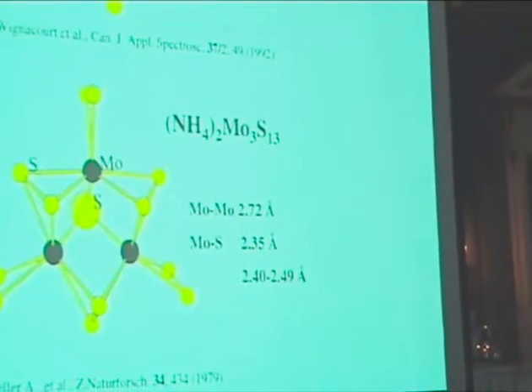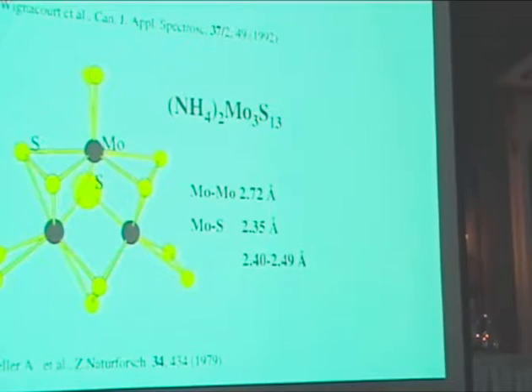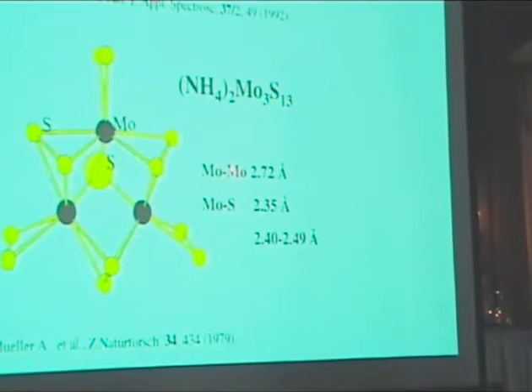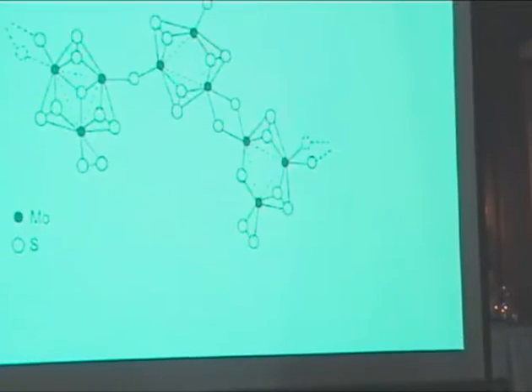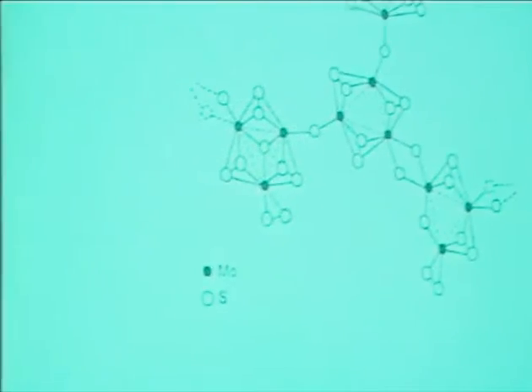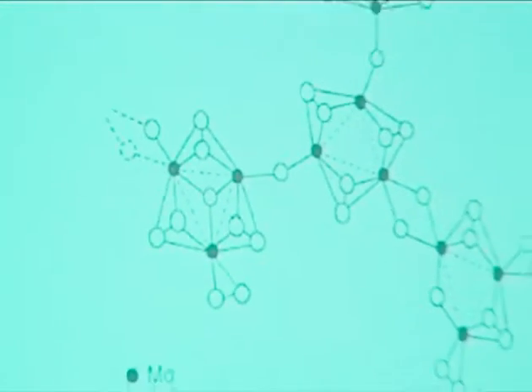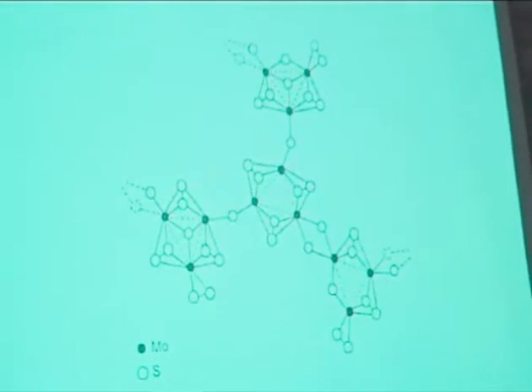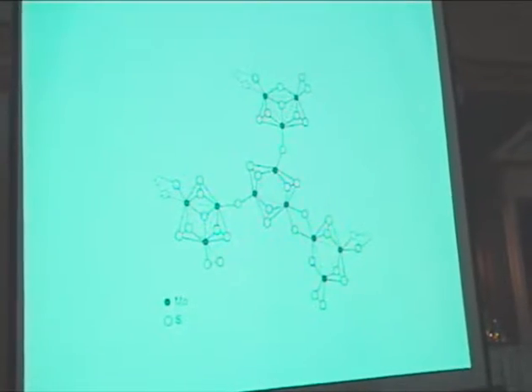And the analysis of the spectrum was that in that case you also have two peaks. One was the molybdenum-sulfur, one was the molybdenum-molybdenum. So we think that the intermediate is an amorphous state. Nobody has ever been able to crystallize this intermediate state. And we believe that it is because it is a mixture of everything.